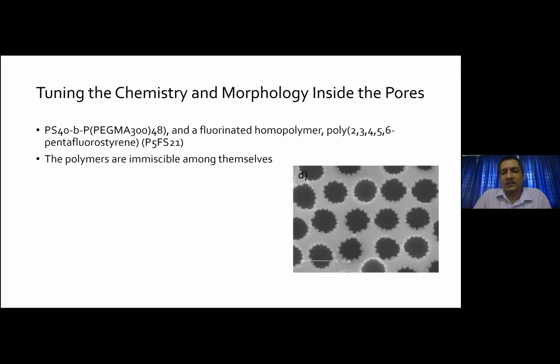Even more interesting work is done by another group, where they wanted to blend three different polymers, chosen in such a way that all three are mutually incompatible. For example, polystyrene, polyethylene glycol methacrylate, and a fluorinated homopolymer. This is pentafluorinated polystyrene. These three polymers are orthogonal, meaning they are immiscible among themselves, and they